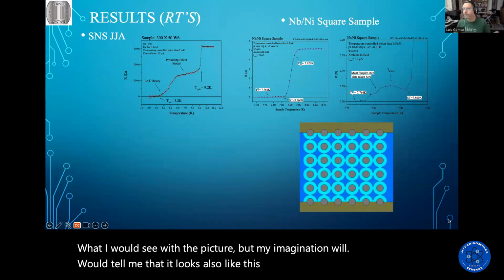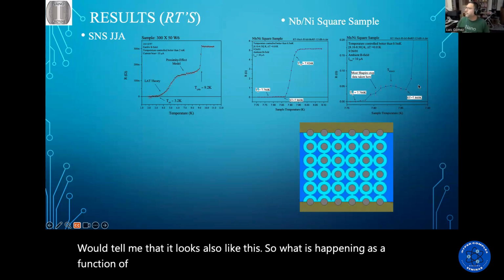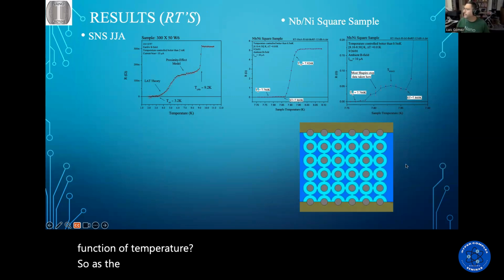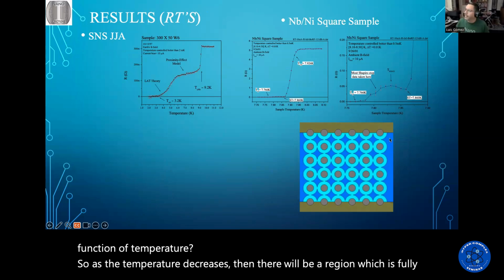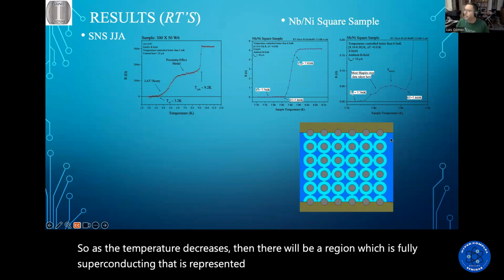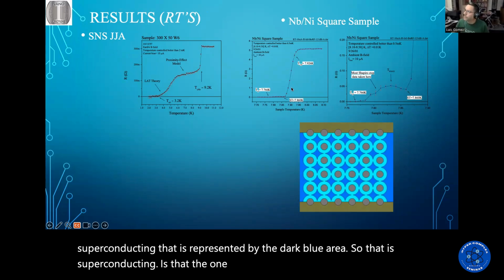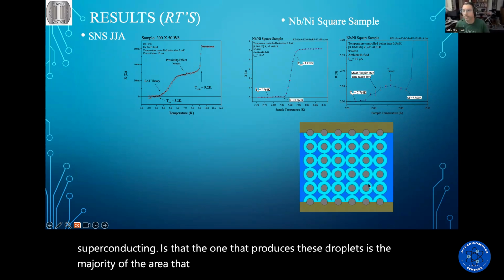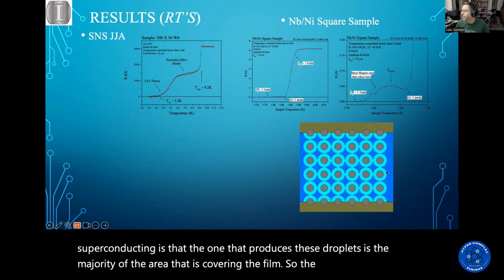So what is happening as a function of temperature? As the temperature decreases, there will be a region which is fully superconducting, represented by the dark blue area. That region that is superconducting is the one that produces this drop. It's the majority of the area covering the film, so the current goes through here.